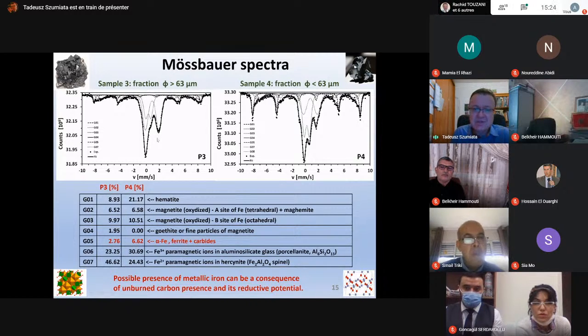But the most interesting feature is the presence of components, not too much, but still visible, which could be associated with metallic iron, or maybe iron carbides too. But from where can we find the metallic iron in fly ashes? The answer could be quite simple.